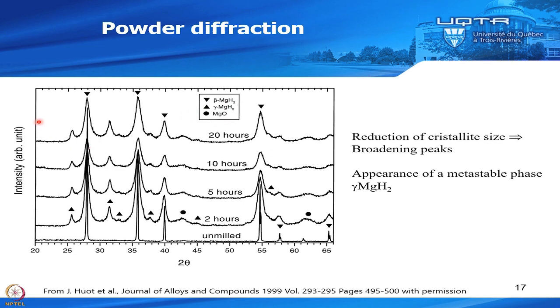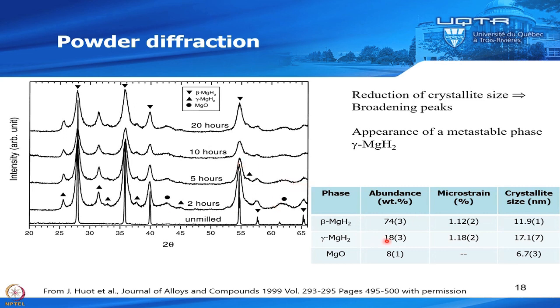So this is a metastable phase of magnesium hydride. The normal phase is the beta phase, the room temperature phase, but the gamma phase is the high temperature, high pressure phase. And you see that you could synthesize it just by ball milling at room temperature. If you do a Rietveld refinement and analyze this pattern, you see that after milling, you have 74% of magnesium hydride and 18% of the metastable phase. And you see a reduction of the crystallite size. Now it's only of the order of 10 nanometer, while before it was polycrystalline, more than 100 nanometer.